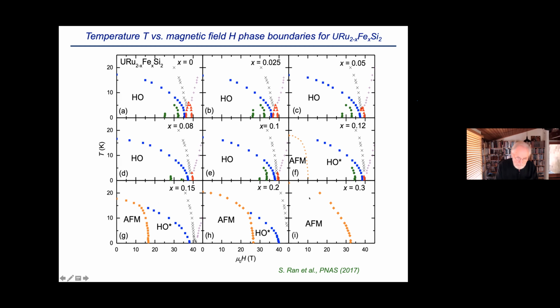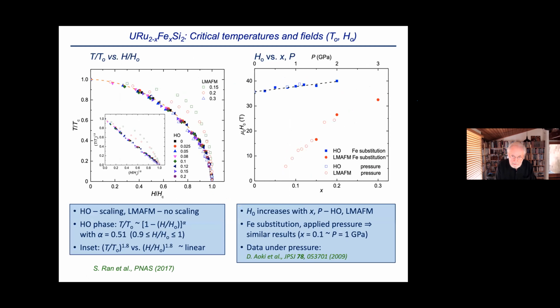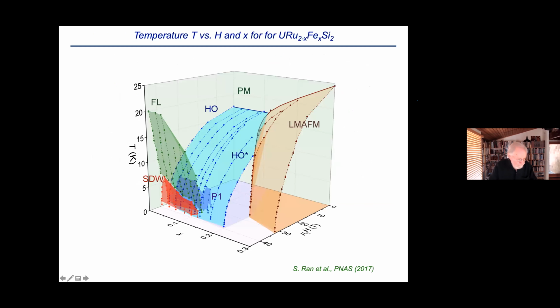So there was some simplification of the previous data I showed you to get to these data, but you can simplify this a little further if you now make this phase diagram where you have temperature versus iron composition and field. And so here, if I look at this plane right here, I'm increasing the magnetic field and I'm suppressing the hidden order in the pure compound. And then there's this phase that has a spin density wave. This is the new phase that I mentioned that's due to this